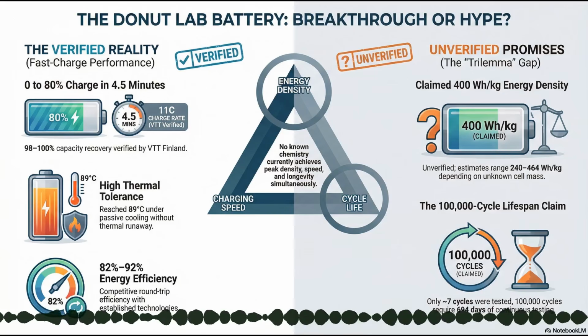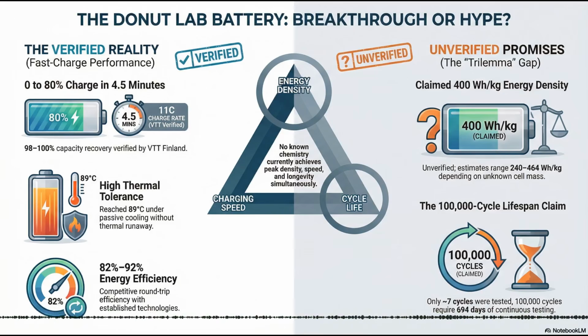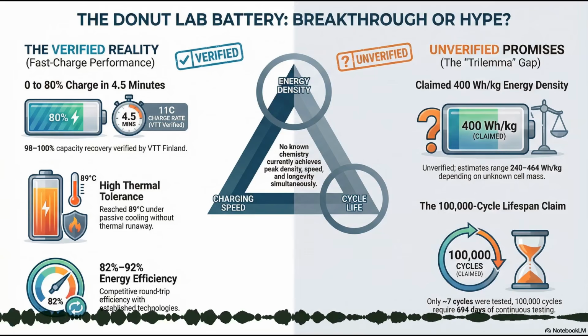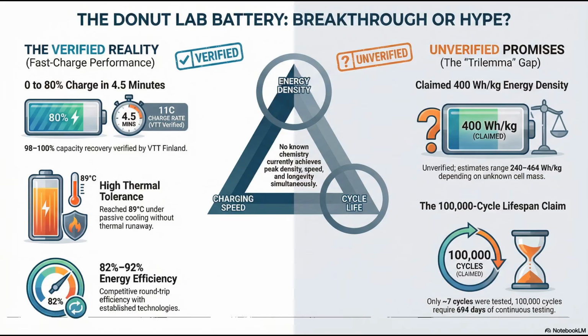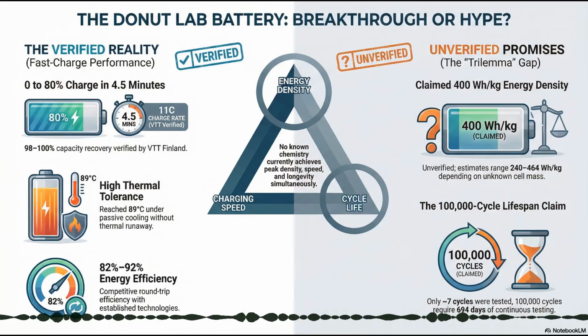You might have zero apparent degradation for 1,000 cycles, and then suddenly microcracks start forming in the solid electrolyte due to mechanical fatigue, or a dendritic short finally pierces the separator, or the contact pressure relaxes and fails. Battery death is rarely a straight line. It's often a cliff. Let's talk about why batteries die. For the newer engineers listening, why is 100,000 cycles so hard to achieve?